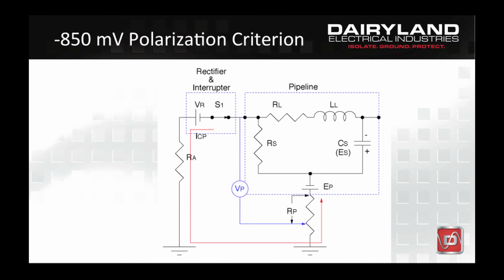This slide shows a simulated potential measurement being taken between the pipe and a copper sulfate reference electrode placed on the ground above the pipeline with the rectifier current on, highlighted in blue on this slide. In practice, the closest one can place the reference electrode to the pipe is to place it directly above the pipe in contact with earth. The problem with the resulting measurement is that cathodic protection current passing through the soil between the reference electrode and the surface of the pipe coating will produce a voltage drop, which is the product of the rectifier current flowing through the resistance labeled R sub P in this slide.